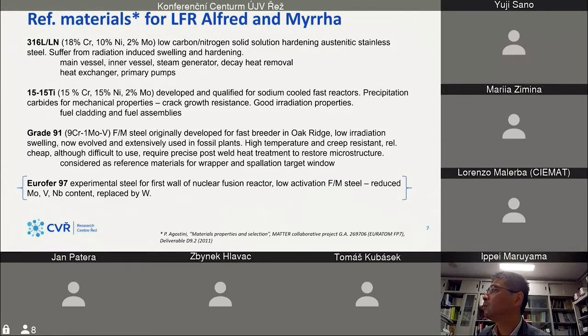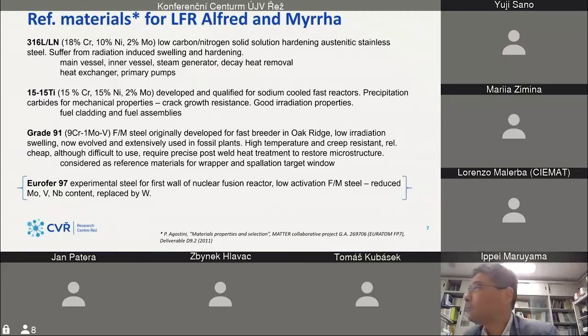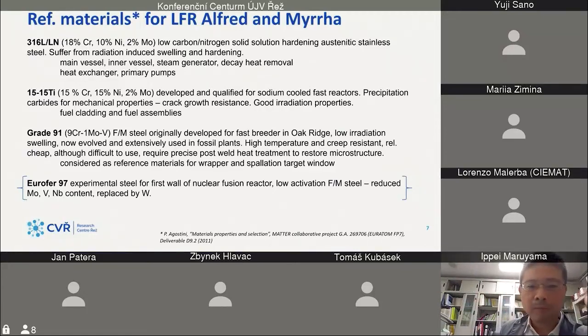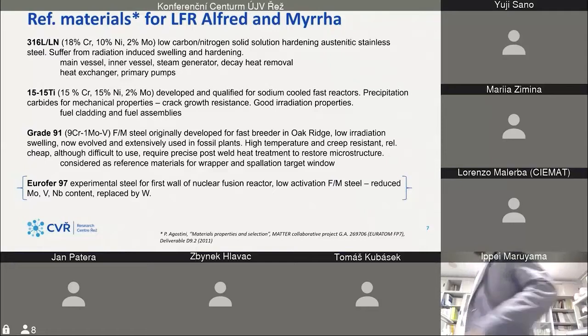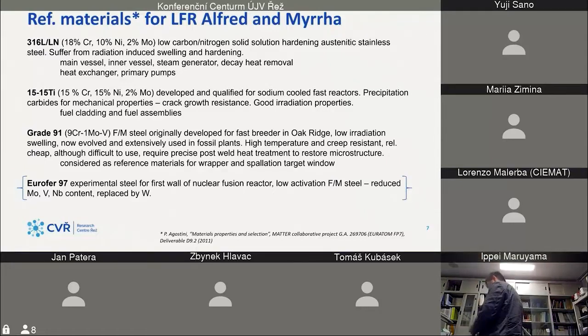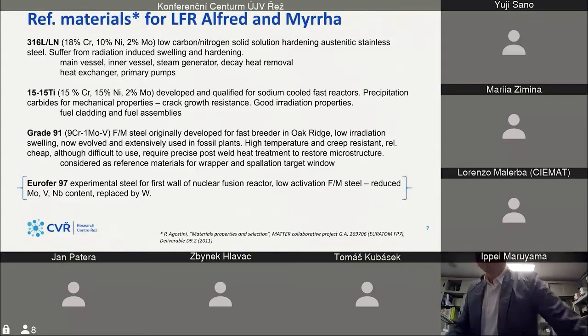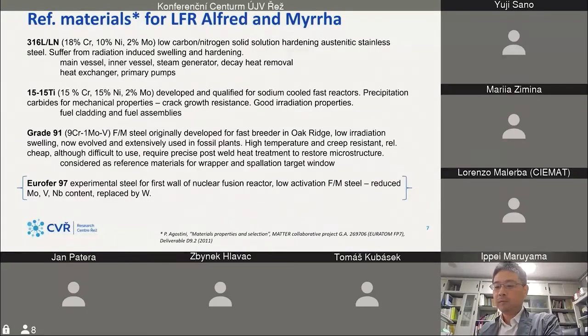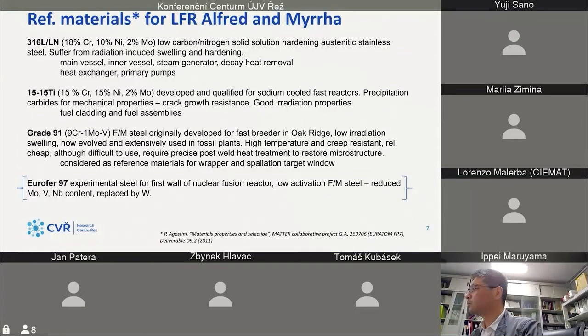There is also grade 91 ferritic steel. It was developed originally for fast breeders, but now it's extensively used in fossil plants. It has a unique microstructure that makes it very high-temperature and creep resistant, but it's very difficult to use because it requires precise post-weld heat treatment. And there is also Eurofer steel, which was not developed for fission reactors but for a demo plant for fusion, with the benefit of being low activated. So as researchers, we decided to test it as well, but it's not an ALFRED or MYRRHA type steel.